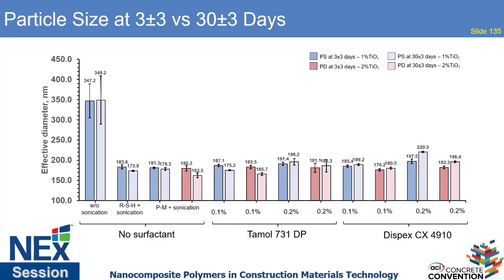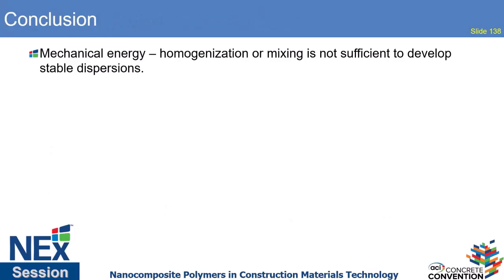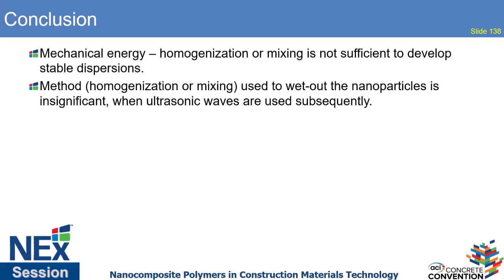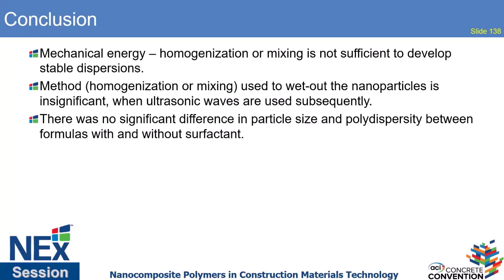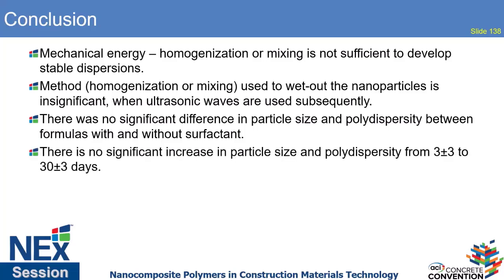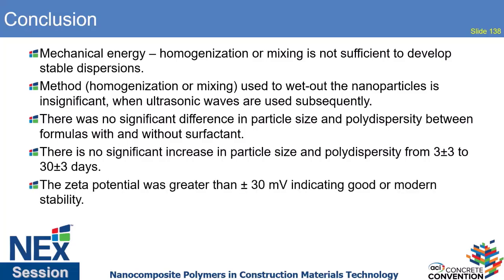From our studies, we could conclude that mechanical energy, homogenization, or mixing is not sufficient to develop stable dispersions. As many other studies have shown, the homogenization or mixing used to wet out the nanoparticles is insignificant when ultrasonic waves are used subsequently. There was no significant difference in particle size and polydispersity between formulas with and without surfactant, and no significant increase in particle size and polydispersity from 3 to 30 days. The zeta potential was greater than 30 millivolts, indicating good or moderate stability.